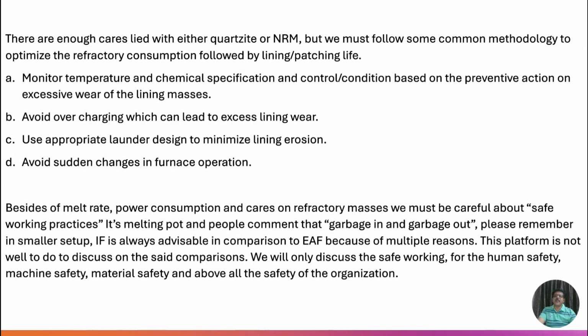There are enough cares specific to either quartzite or NRM, but we must follow some common methodology to optimize the refractory consumption, followed by lining or patching life. Monitor temperature and chemical specification, and control conditions based on preventive action on excessive wear of the lining masses. Avoid overcharging, which can lead to excess lining wear. Use appropriate launder design to minimize lining erosion. Avoid sudden changes in furnace operation.